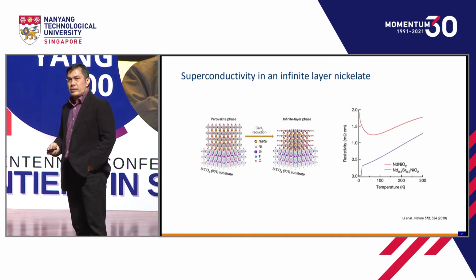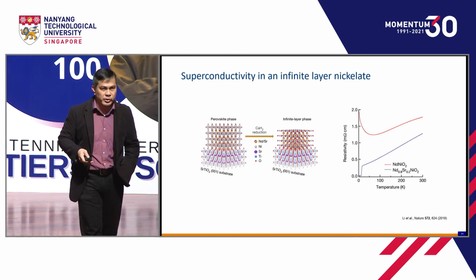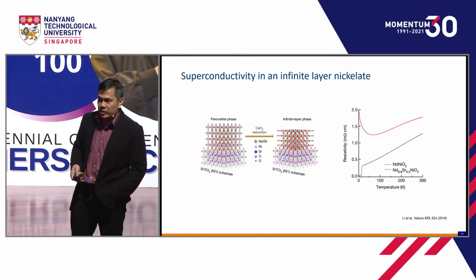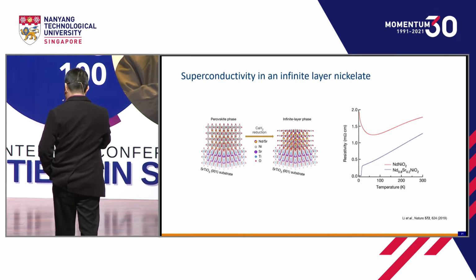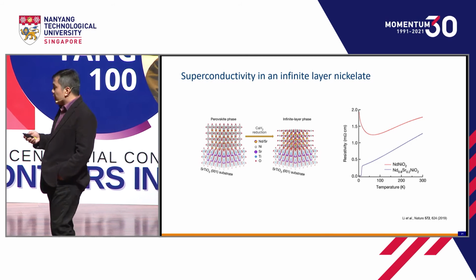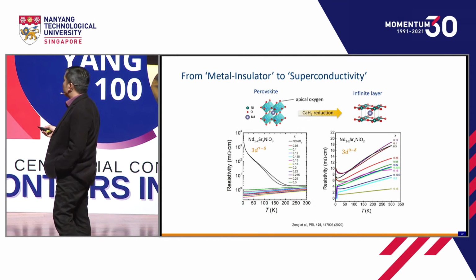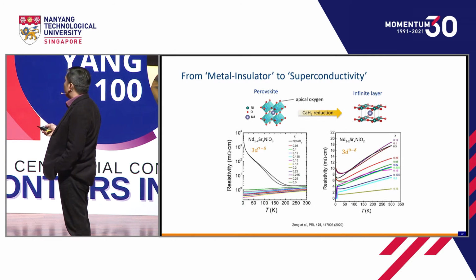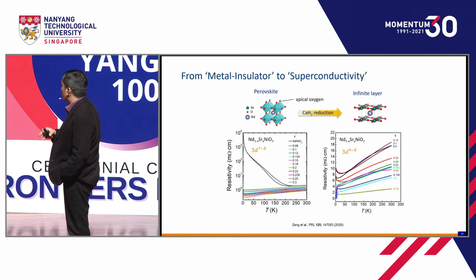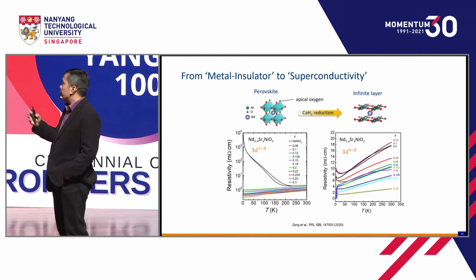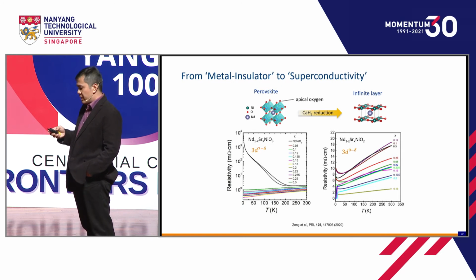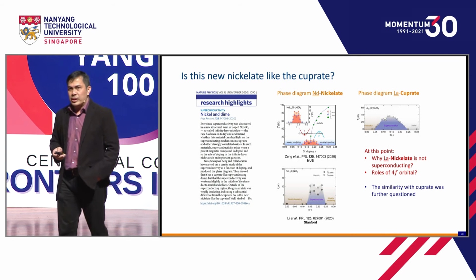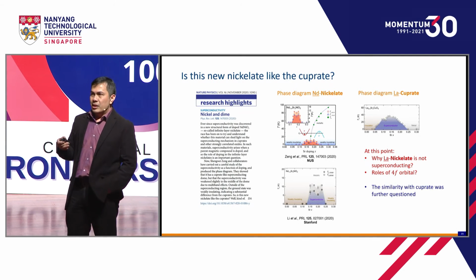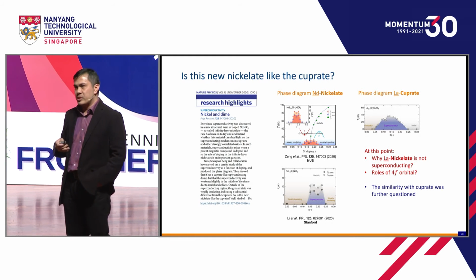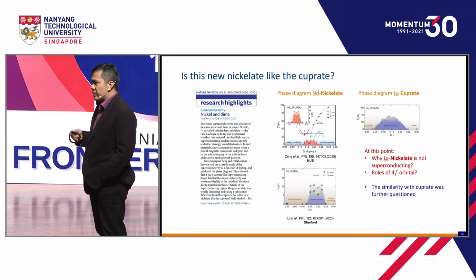Well, in 2019, with this approach, superconductivity was observed for the first time in these nickelates, after 30 years of research trying to produce superconductivity in this nickelate. It was first reported by the Stanford group, Harold Hwang. And we immediately produced the same superconducting state in this infinite layer nickelate, and we can vary the electronic count by doping, and produce this superconducting phase, a complete superconducting dome of this infinite layer nickelate, based in this case on the neodymium atom. It was very nice. So now we have been able to robustly produce this sister of the cuprate in this nickelate.